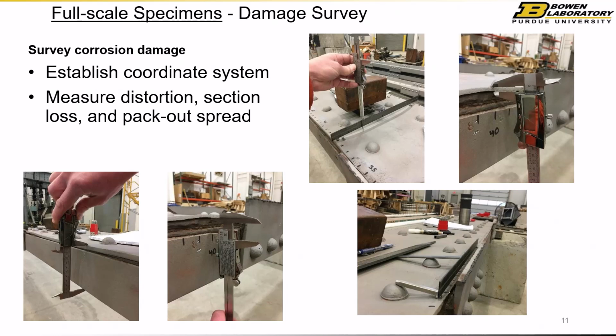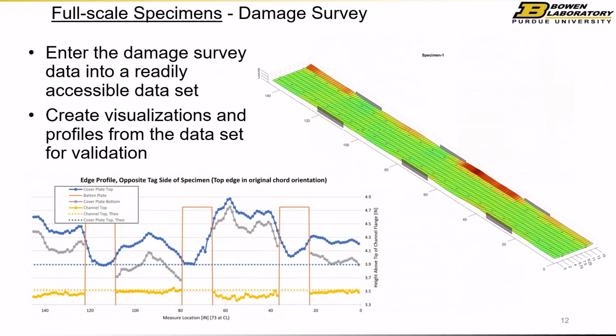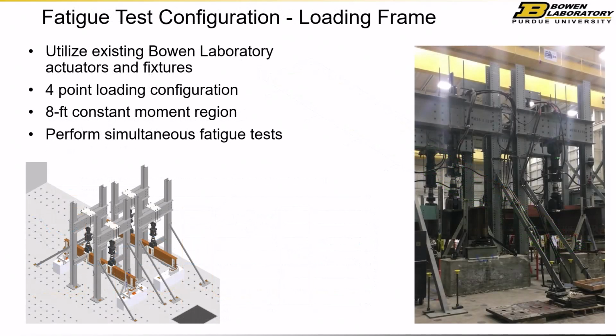And we did this by hand. We tried to do some of the photogrammetry, and it worked okay, but it just wasn't working out as good as we would have liked. So we took the time to go and lay out grids and so forth and measure all that damage. And you take all that information, and then you can map it out, right? And get a feel for where most of your damage is. And that becomes useful to put into like finite element analysis, right? You can map all those surfaces in there. But the point is, there was a lot of damage, and there was a lot of section loss, right? So these are severely damaged components.